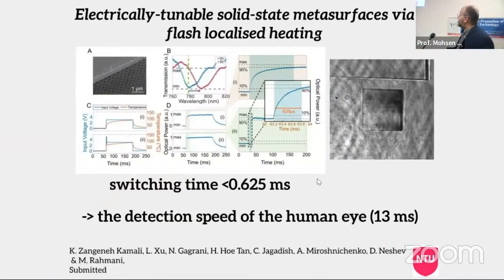Sorry, I forgot to update it. This was actually published at the end of last year, in Light: Science and Applications. So here what we did, we solved that issue. We used a layer of ITO, and we have the silicon underneath. ITO is a conductive layer which is transparent, but it has some resistance. So when you apply voltage to this, because of this resistance, you generate some heat, and that heat we transfer to the metal surface, and we do the same concept. We shift the resonances, and then we can have this small patch or a small metal surface that can be turned on and off.